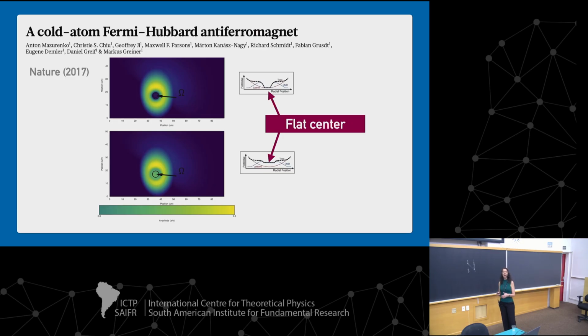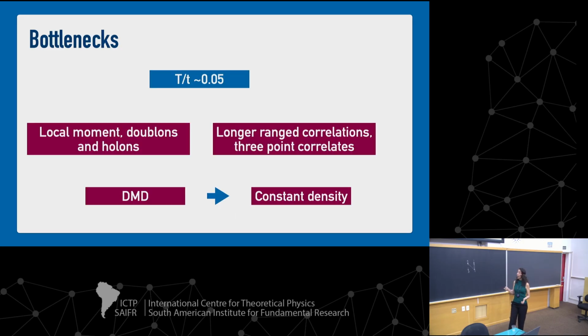It can lead to easier understanding of what the physics is. It's not that going away from half-filling is not interesting, it is. Superconductivity doesn't happen at half-filling, it happens away from half-filling, but we want to have a steady density. We want it to be the same over a wide region, so we can understand. It doesn't have to be half-filling as in his experiment, but it has to be constant over a region of space. So the bottlenecks that I mentioned in the beginning were temperature, and now this temperature has been achieved this year. It's not clear to me if it's reproducible with attractive interactions, with spin imbalance, with other geometries, and what the needs are to reach this temperature.